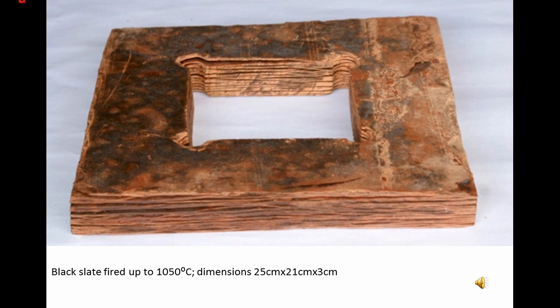After firing up to 1000 C, the color of the black slate changes from black to rose and rusty red, but the fired piece keeps its shape. Fired up to 1080 C, the black slate piece can expand 100%, or even more, depending upon how the pieces are positioned inside the kiln. If pieces lie down on a face parallel to the lamination, expansion amplitude is lower than when the black slate piece lies down on a face perpendicular to the lamination.